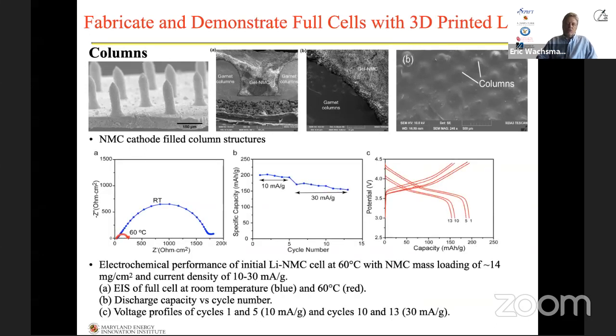This is some of the electrochemical performance data at room temperature. This is a plot of the imaginary versus real impedance on the left in figure A there. We deal with impedance because it has both a resistive and a capacitive component to it. If it was just a simple metal, then it would just be a resistance. And of course, the resistance and therefore the impedance decreases as the temperature goes up. So you see room temperature cycling and 60-degree cycling.